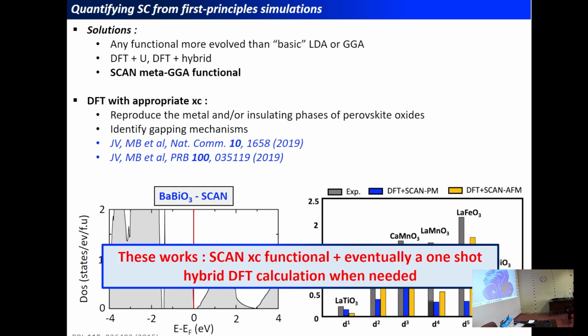So in the works I will show you, I will preferably use the SCAN functional because it's a parameter-free technique, so there is no adjustable parameter. We don't have to fit any U potential or anything. It's just the functional, we use it as it is. But sometimes, especially on the nickelates, SCAN is not sufficient to correctly predict the band gap amplitude, and so we will use more elaborate techniques such as hybrid DFT, but that are much more computationally demanding.